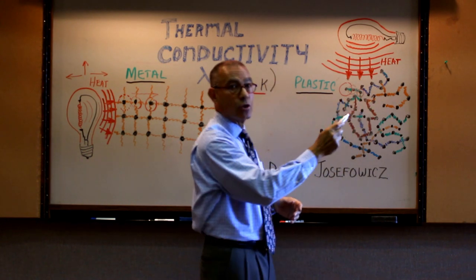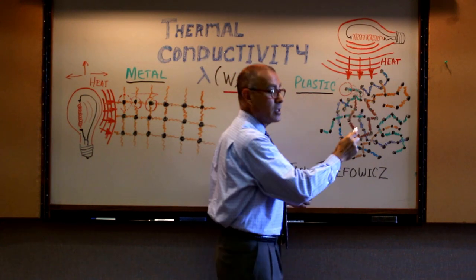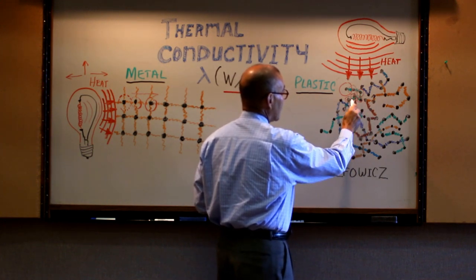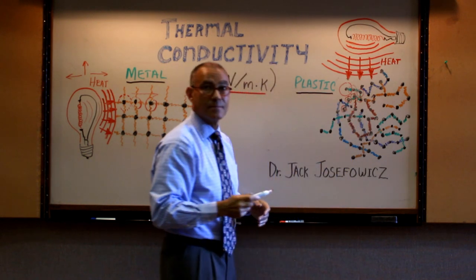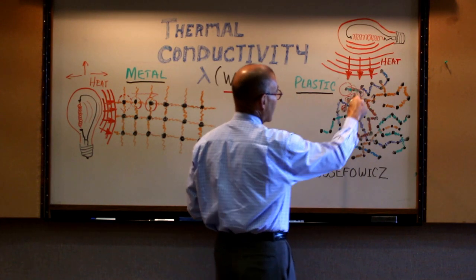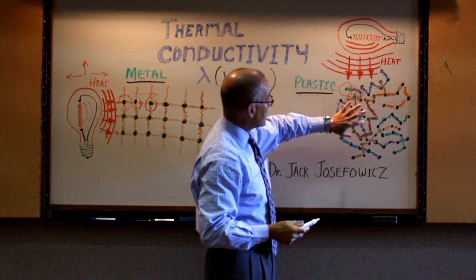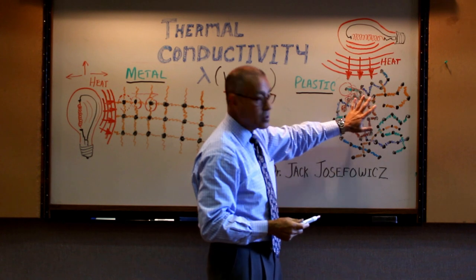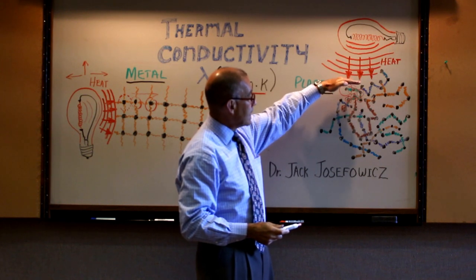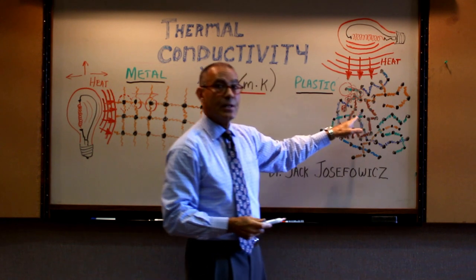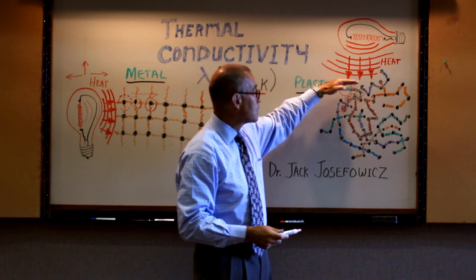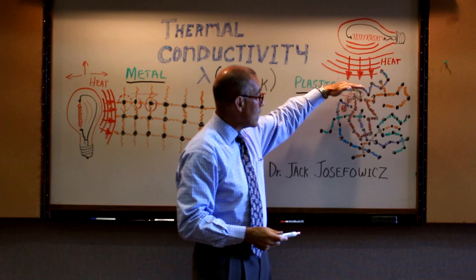But as you can see, if we follow a particular molecule routing, it doesn't necessarily efficiently move from one side to the other side, but it follows its spaghetti-like random directionality. So we go, in this case, like this, instead of straight through, we go like this. And other atoms, which are oriented in different directions, and coiled, and so on and so forth, you can see that the thermal energy will very inefficiently move from one end to the other end, and so the thermal conductivity of this material is low, which impacts the slower rate of energy transport of heat energy from one end to the other end.